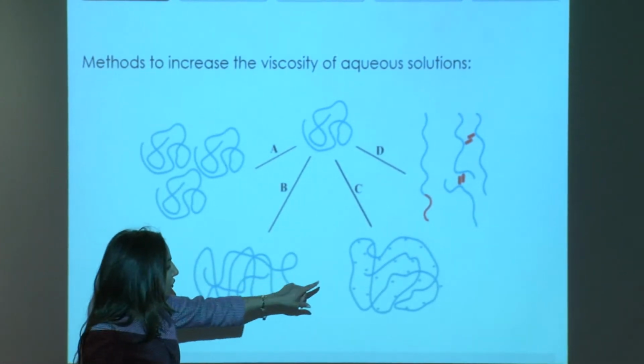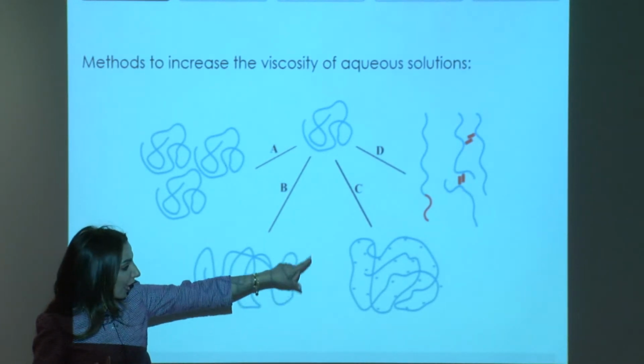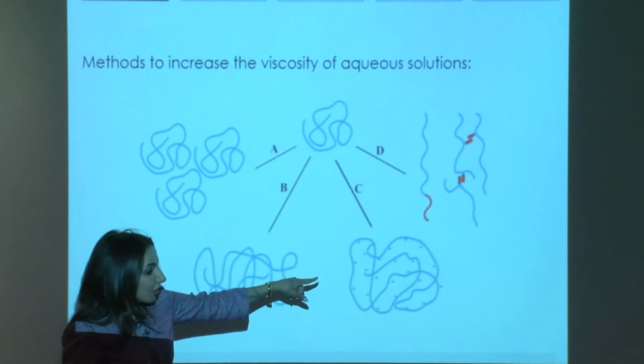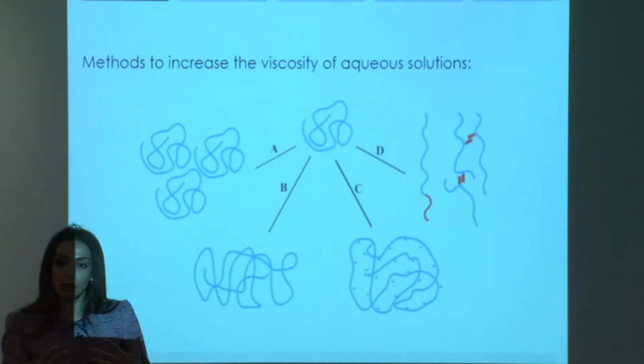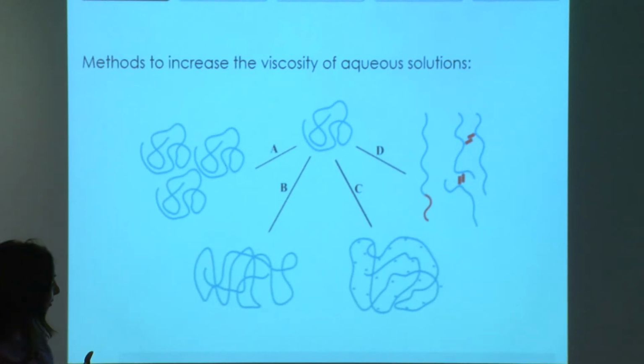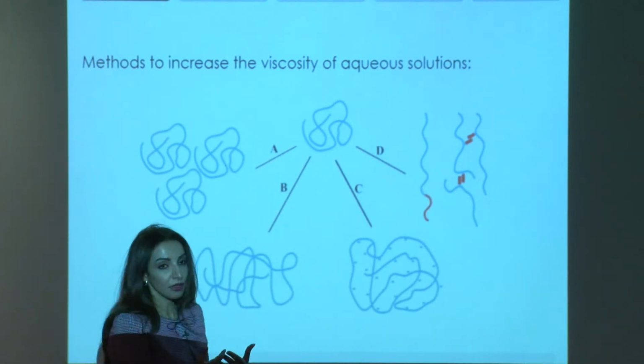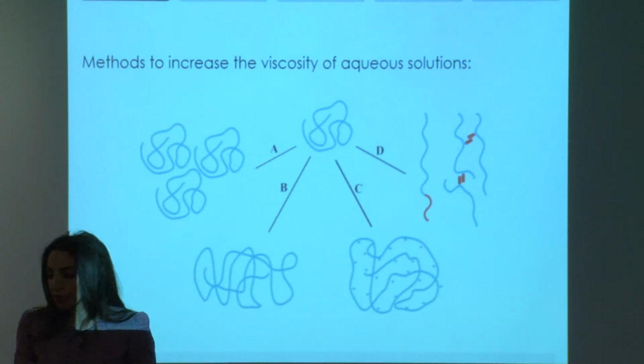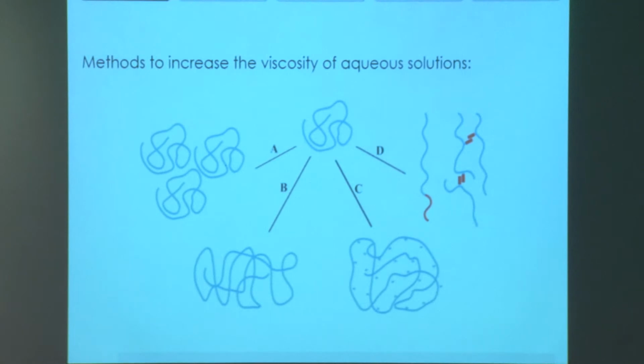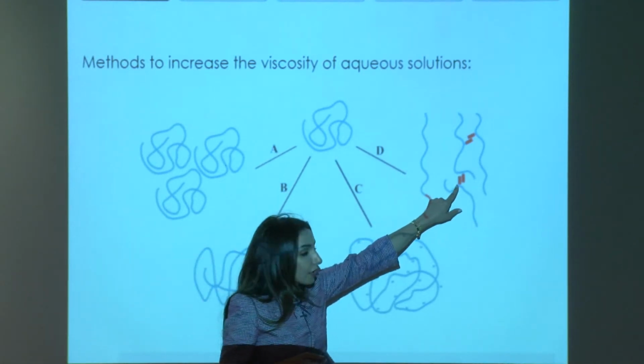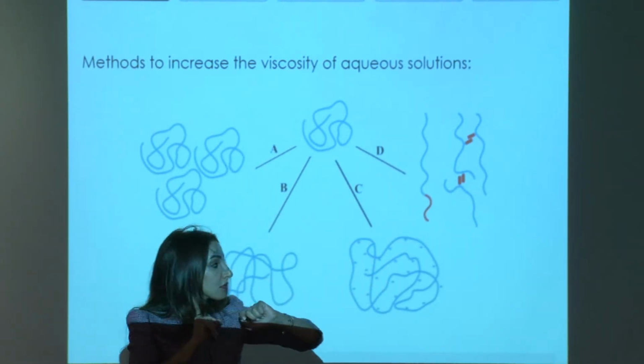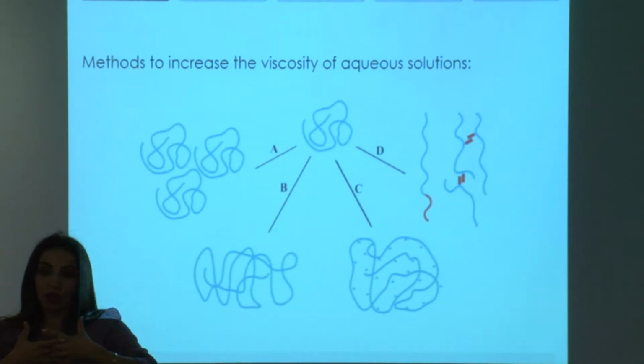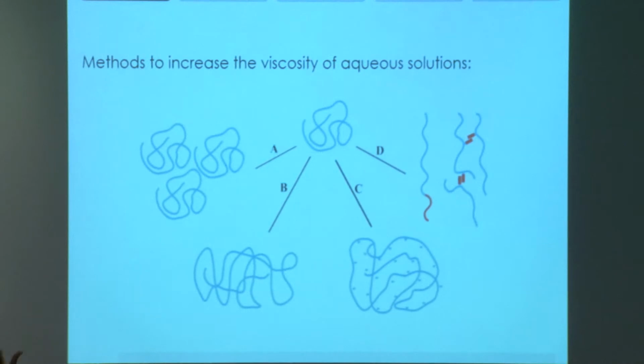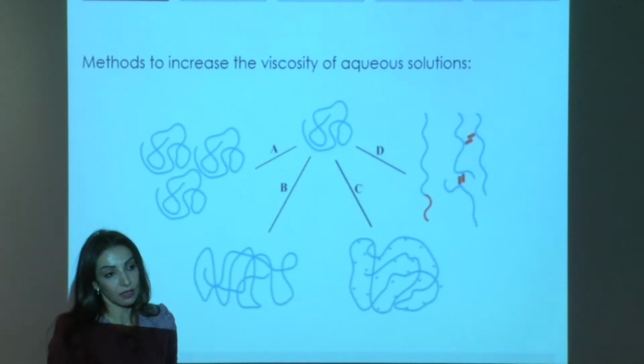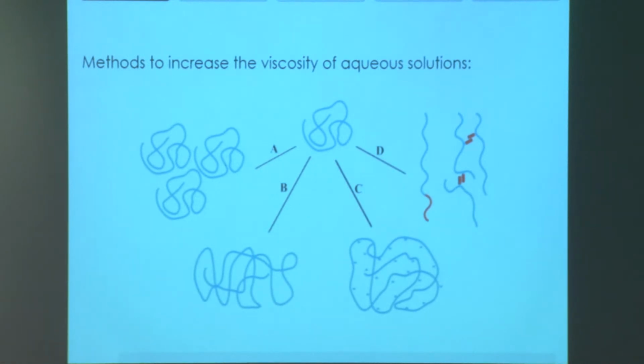Another approach is to introduce charge moieties along the backbone of the polymer. These charge moieties will increase the electrostatic repulsion between them and will increase the hydrodynamic volume of the polymer and then increase the viscosity. The new approach now is to introduce hydrophobic groups in the backbone of the polymer. So these hydrophobic groups will interact with each other when any high shear or high force is applied and then will increase the viscosity.